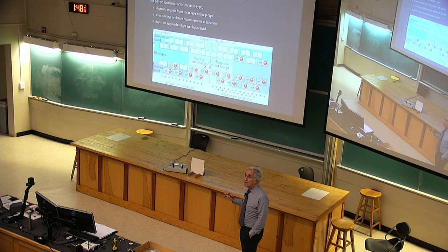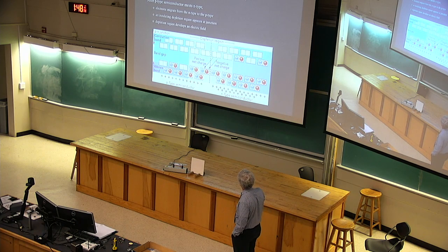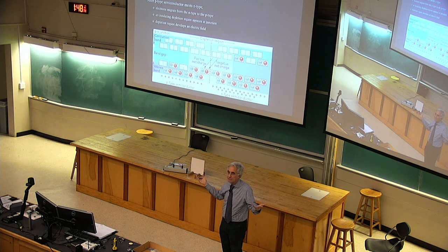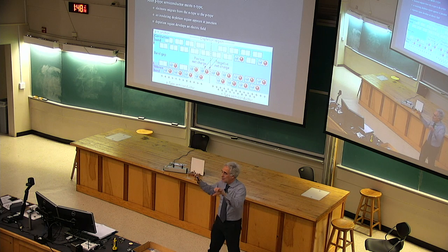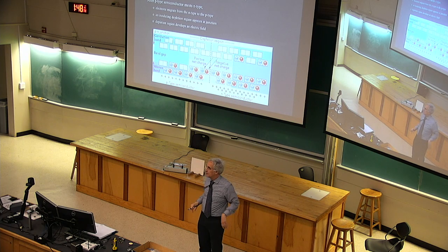It has all the valence levels full, and all the conduction levels empty by virtue of this migration and settling. And this is called the depletion region. It's an insulator again. It doesn't carry electric current. That PN junction loses its ability to conduct electricity right there in that central region.